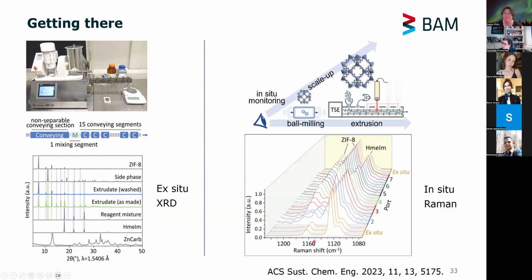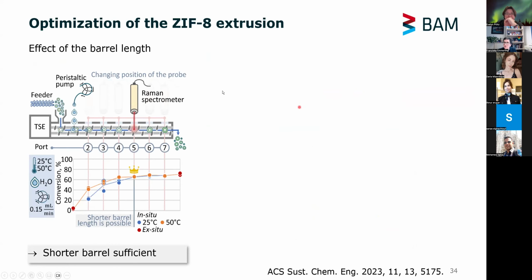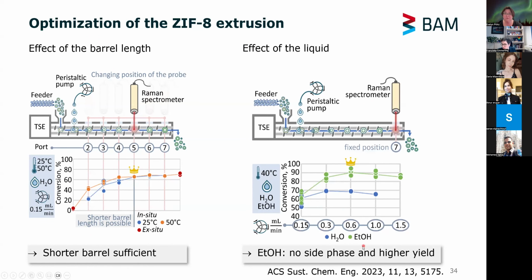And then we have to check it also using in situ techniques in this way with Raman spectroscopy, and we can again monitor the bands belonging to the ligand and then to the final ZIF-8 compound. So everything is set up. Now we need to optimize our parameters, and you can see here that this is now in sketch mode. You can see the little crown indicating the best conditions. So first question, do we need the whole barrel length? Can we go with a shorter barrel? See, that looks okay. Conversion is not that high. Later on, we changed from water to ethanol, and then you can see, okay, this is not bad. It leads to a higher yield, and also we can avoid the annoying side phases.